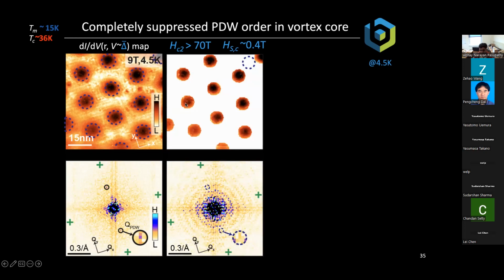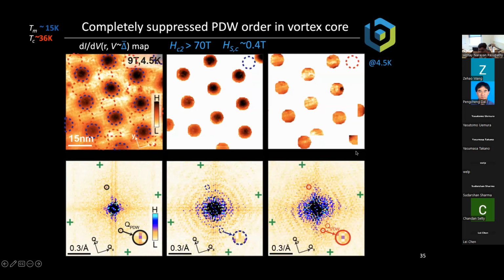And if we take a Fourier transform of just these regions of the sample, our modulated superconducting behavior is gone on the inside in the vortices. And just to be sure that this is not an artifact of our masking procedure, we can just shift the mask from this blue region down, we can just shift the same mask down, take the Fourier transform of these regions, and then you see this feature reappear at that wave vector.